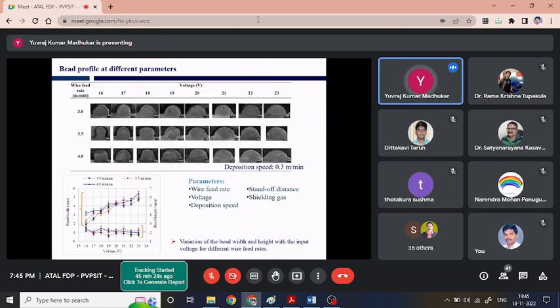Now, if we calculate the amount of energy input, in this case we've been giving nearly 0.33 kilojoule per mm, and in the previous case it was close to 0.21 kilojoule per mm. So certainly in this case, without changing the material property, we are giving much more energy. So there is a high chance of short circuiting, and because of that the current increases wherever the short circuiting happens, and we get non-uniformity in deposition. Probably in all these cases, that kind of situation has been happening. The bottom line here is we need to optimize the parameters for the additive manufacturing application.